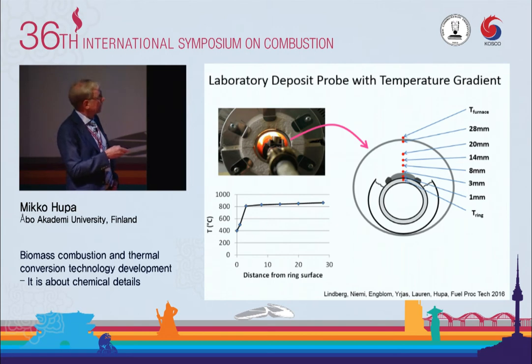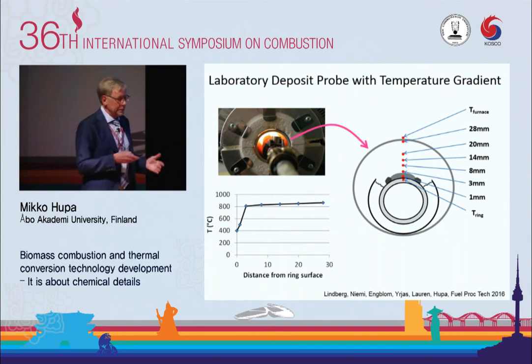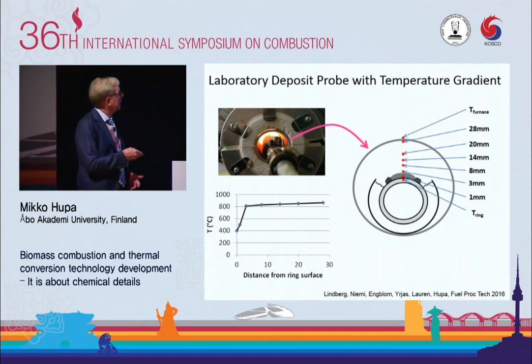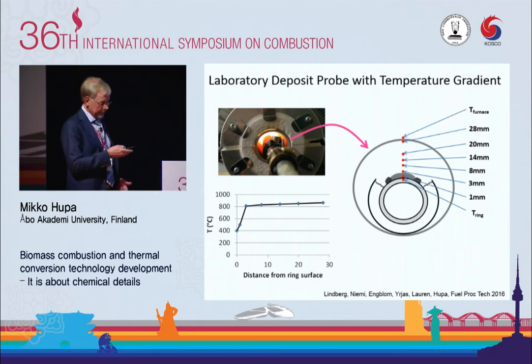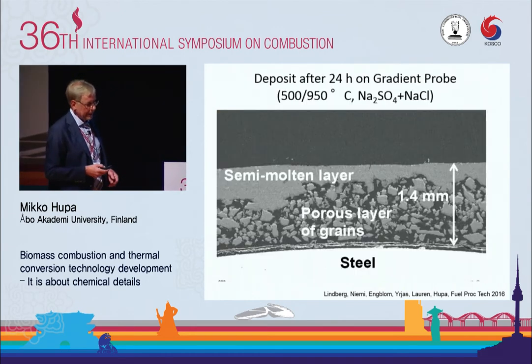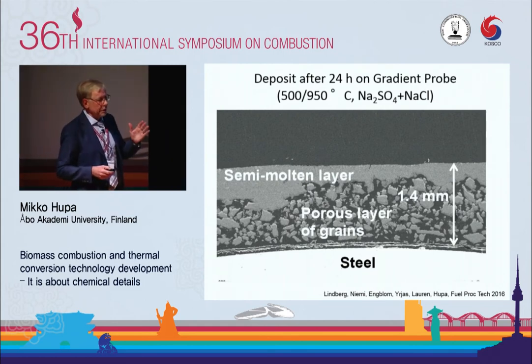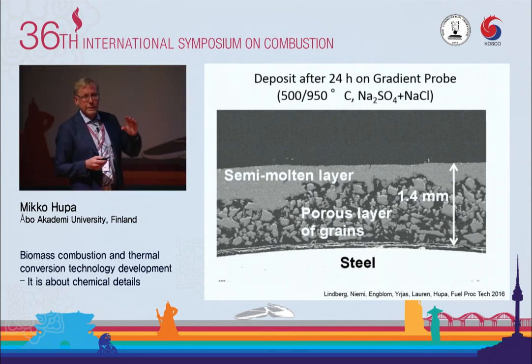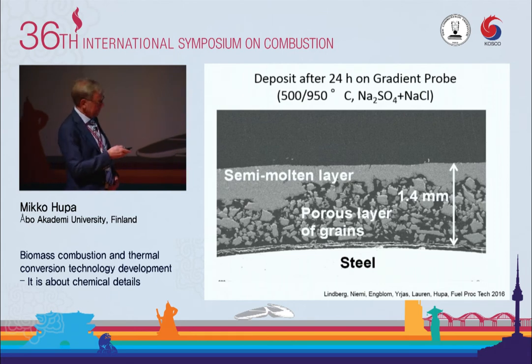This is not a very clear picture, but the idea is we have a cooled pipe where the inside temperature was 500 degrees, for instance, and then we can put our deposit sample here. But we have to cover the rest of the tube for heat transfer reasons. And then if we have only that part open and we have a hot furnace around, we can create something very similar. And we can have a gradient inside that deposit. And it was interesting. If we put a layer of salt on that gradient condition and let it be there one day, this is what we saw.